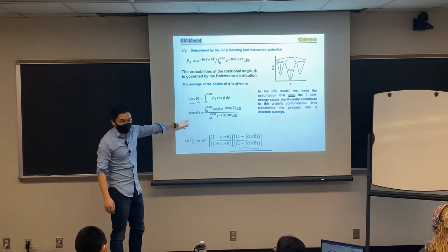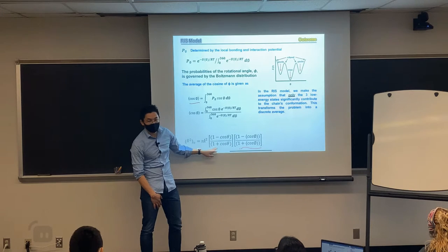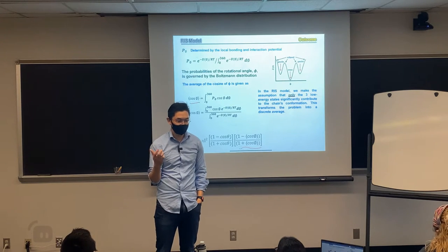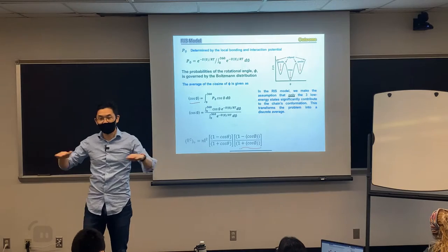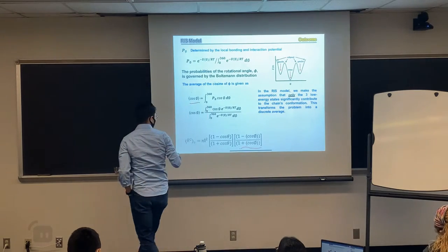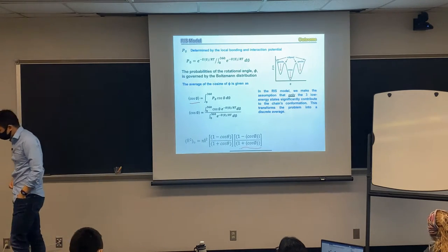Once you get this averaged phi angle through your energy diagram, then we can plug in to see the expansion factor that comes from this rotation isomer. You can see these two equations are quite similar, which means the expansion factor from bond angle and rotation isomer angle have a similar effect, resulting in chain expansion. If the rotation isomer state always prefers a deep trench, then your chain will be more expanded as well. If it's a flat curve, then average cosine theta will be 0, then 1 minus 0 over 1 plus 0 means there's no expansion, okay? That's how you can read this particular technique.